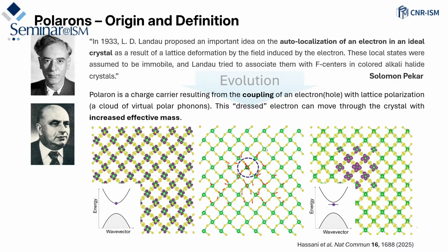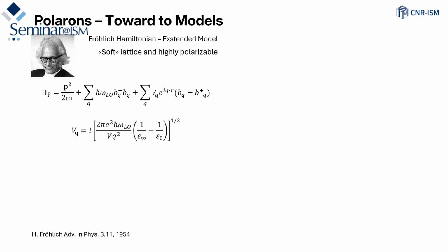This concept was investigated in more detail by Pekar, who gave this very beautiful definition, which is the strong coupling of the carrier with the lattice polarization. So we can imagine the carrier covered by this cloud of virtual phonons. And the result is that we have a carrier with increased effective mass, so the mobility is lower than what we can expect from a free carrier in a band.